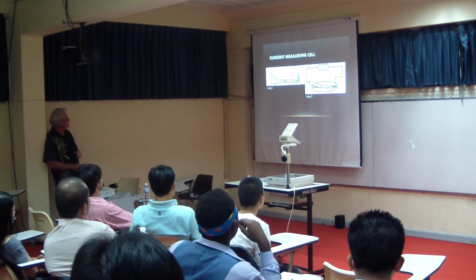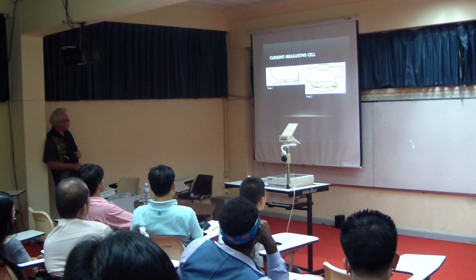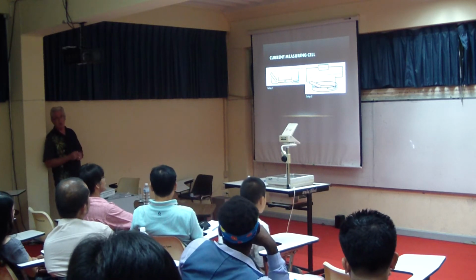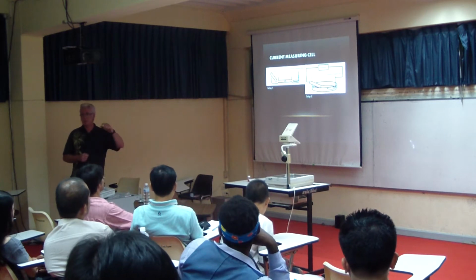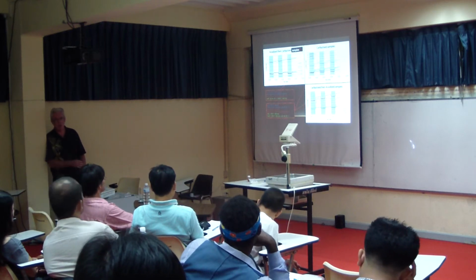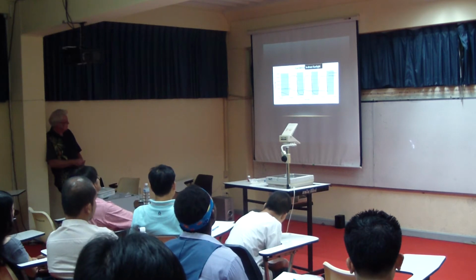All we did was we measured some current when we shone a light on it, and tomorrow we're going to do some hydrogen evolution measurements here on these samples. But you can see that depending on what treatment we did, how much carburizing we did, whether we carburized it first or anodized first, we've got different jumps in current. You can see this one quite good. And in indirect sunlight, maybe 90 microamps jump when the light shone on it. So we're very hopeful about this one.